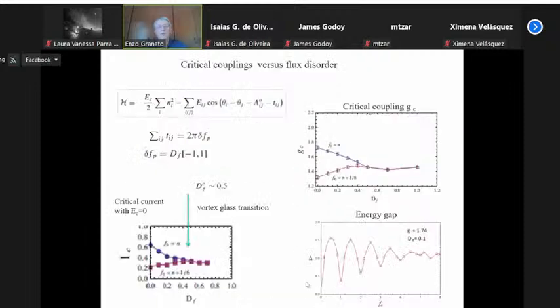So now we use this model and perform numerical calculations with a particular representation of the disorder in the arrays. On the right are the results for the critical coupling as a function of the effective disorder, and the red line is for a frustration of 1/6, which is close to the critical point for the magnetic field induced transition observed experimentally in the system. We also add a calculation for the case in which the average frustration is an integer, and you see the behavior is different. It increases for a high order rational value and decreases for an integer value.